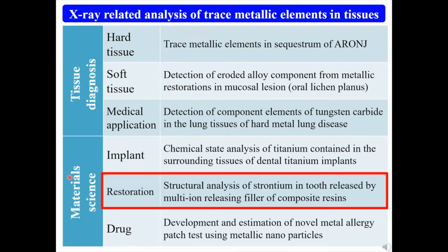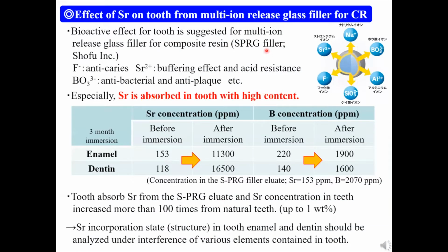We applied this X-ray absorption spectroscopy to the estimation of composite resin fillers. The next topic is the behavior of ions released from composite resin fillers. Some types of composite resin fillers provide bioactive ion release, not only fluoride but also strontium, boron, or others. Especially, strontium ion was suggested to have various positive effects, such as buffering of the oral environment and improvement of acid resistance of the tooth. In a pilot study of ion absorption into teeth, we found that strontium was drastically absorbed into both enamel and dentin.